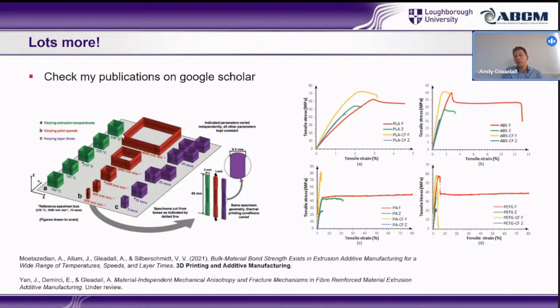And I'm not saying this is for all materials or anything like that. It's just that unless you measure the bond area and check, you don't know. So we did, and now we're testing, does this translate to different conditions? So here we printed the same material, same printer and everything, with temperature ranging from 180 to 240, with speed ranging from 250 to 4,000.